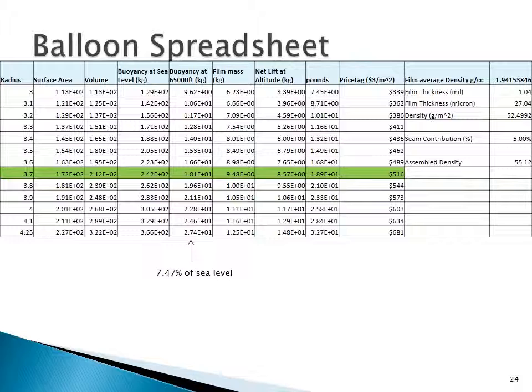And I've calculated the loss rates out. We'll talk about that later. On the balloon spreadsheet, where I figured out the optimal size balloon, given the size I have at 7.47% sea level buoyancy because of the density change up there, a 3.7 meter radius balloon seems reasonable. That gives me a little over 8.5 kilograms of payload, so it's well matched to what I need.